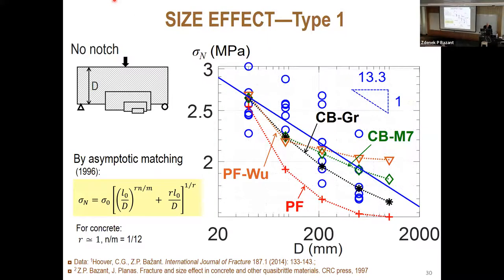Now there is another type of size effect when you don't have a notch. Fracture starts when a sufficient process zone is developed, basically RVE size. So the process zone grows and that causes also transition, but much weaker. So it's the asymptotic formula realistic here, published, of course, derived asymptotically for asymptotic properties. And it gives a curve which flattens eventually to Weibull size effect, statistical, but not in this range. Statistics cannot intervene here because you have only one possible choice for material failure, not many choices to take statistical conclusion. And you see the data here, typically these kind of data are more scattered, but there is a clear trend. This is the mean, formula fits the mean.